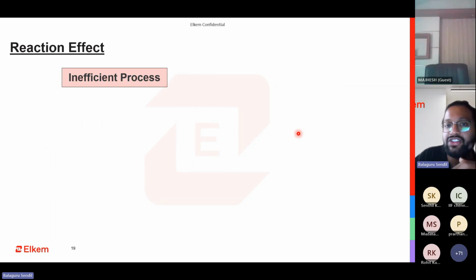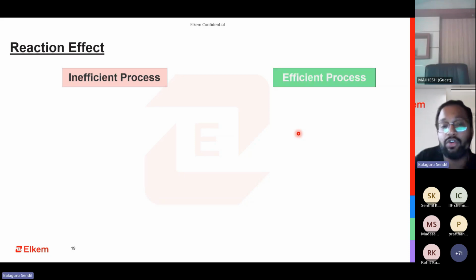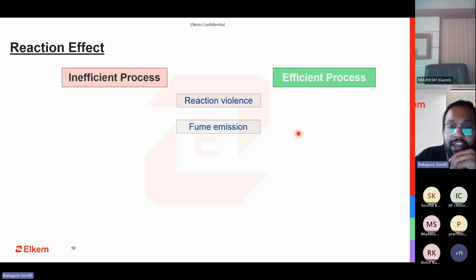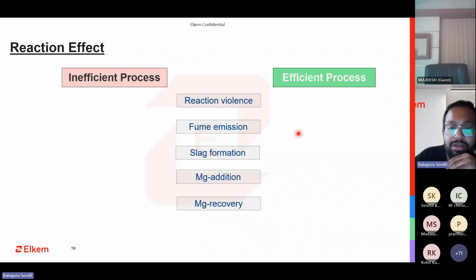To have a calm reaction violence, the first thing is to have a lower magnesium, but your process demands a certain high amount of magnesium. Then you need to have the correct amount of calcium to balance it. This is in terms of FeSiMg. Additionally, there are a few other parameters which influence your reaction. The first, reaction violence, fume emission. These are the various parameters that I have plotted here: slag formation, magnesium addition, magnesium recovery, inoculating effect.